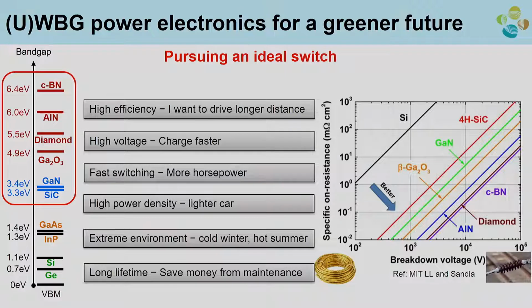And how about at a fixed power, at a fixed voltage? For example, if you want to operate your electric car or any electric equipment at 1,000 volts, essentially, if you use silicon carbide, SiC, you can realize about 3 orders of magnitude less resistance, right? Because the loss of energy is proportional to the resistance. So this indicates that wide bandgap and ultra wide bandgap semiconductors can save you 3 orders of magnitude less energy compared to silicon technologies.